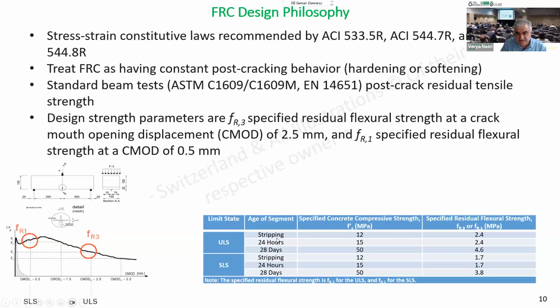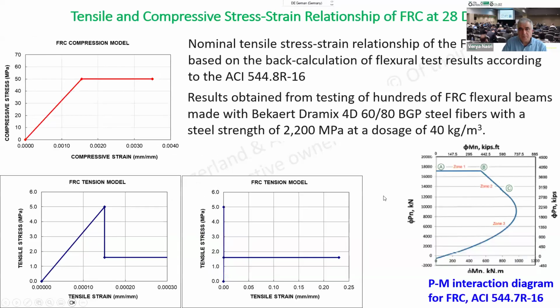And then here, this is a different time. The strengths are different. Obviously, stripping is about 4 to 6 hours, and then 28 days. So you see in this particular case which kind of numbers we have. And then this is the model I was talking about. We said our concrete was 50 MPa. The model for compression is linear to 50 and then constant.